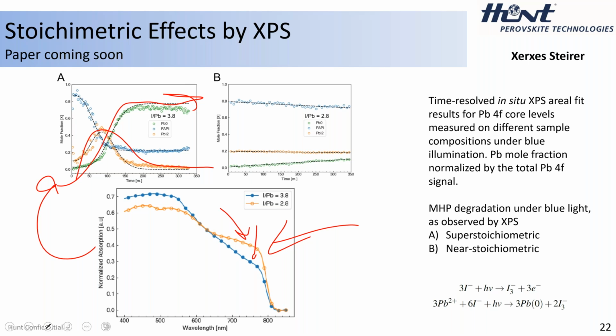Now, if you compare this to a near stoichiometric composition, nothing really happens. The lead iodide, there's a little bit in the initial measurement. That's from fabrication. It doesn't really increase. It decreases just a little bit. We see the growth of a lead zero signal there in the green, but not a lot, just a little bit. And the perovskite persists quite strongly. I will also indicate that if you did this with red light, you would see no decomposition at all, or even less. The blue light tends to drive the degradation. If you want to know why, you'll need to read the paper when it comes out. I'm just giving you a little teaser here.